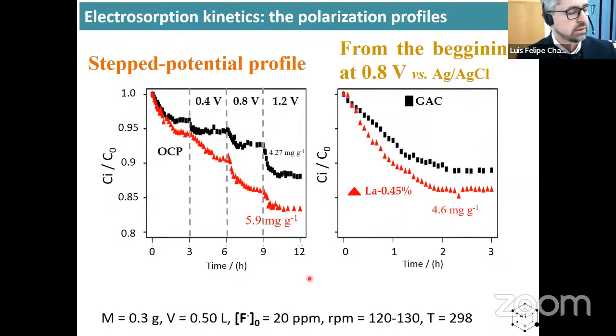In this study, you can appreciate the electrosorption kinetics by potentiostatic control of the anode under the application of a step potential. A step potential means that you wait a little bit at the beginning without electrical stimulus, until the system is in equilibrium, and then you start the polarization. In contrast, in this case the polarization is from the beginning, so you don't wait for equilibrium. The moment you put the electrode in solution, you start the polarization.